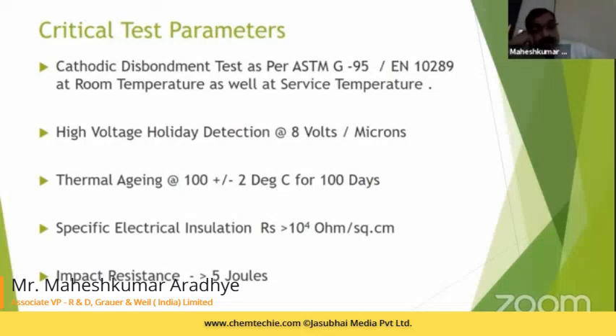Now, if you look at all those test parameters, the coating which you design should meet all these requirements, which clearly shows that it needs a very high degree of electrical insulation. It also shows that it should have a very high degree of adhesion to the surface. It should also have a specific electrical insulation, which are the most critical parameters for any protective coating. That's the reason not all mastics, not all solventless epoxies, not all types of glass flake filled coatings can work in this particular specification. You have to design a coating system which meets the specification of BS EN 10289.